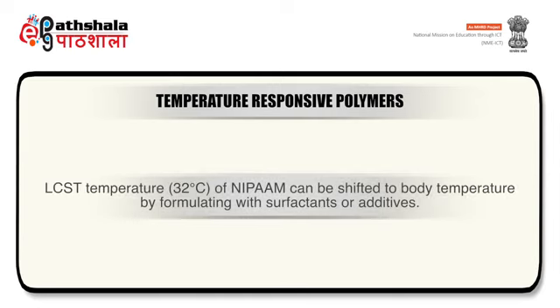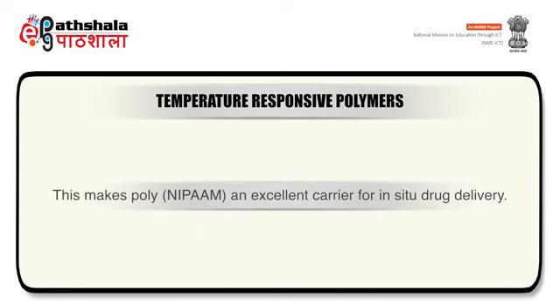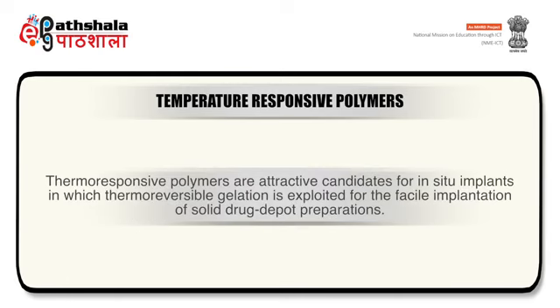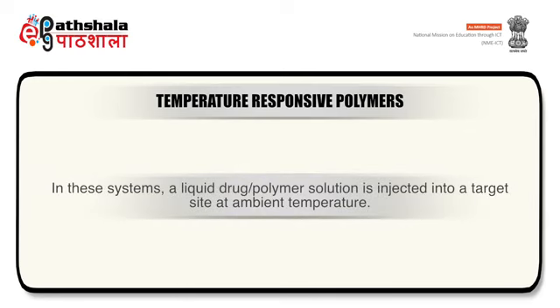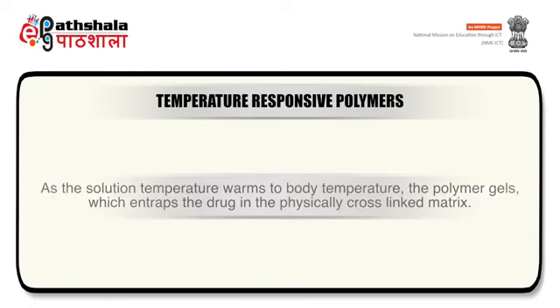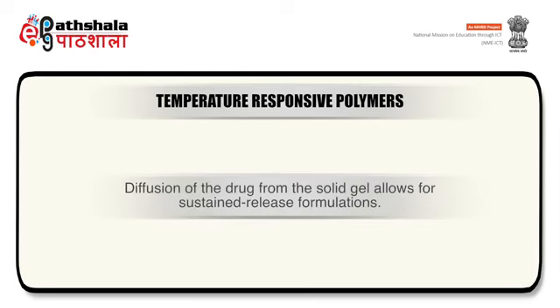LCST temperature of NIPAM, that is 32 degrees Celsius, can be shifted to body temperature by formulating with surfactants or additives. This makes NIPAM an excellent carrier for in situ drug delivery. Thermoresponsive polymers are attractive candidates for in situ implants in which thermoreversible gelation is exploited for the facile implantation of solid drug depot preparations. In these systems, a liquid drug polymer solution is injected into a target site at ambient temperature. As the solution temperature warms to body temperature, the polymer gels, which entraps the drug in the physically cross-linked matrix. Diffusion of the drug from the solid gel allows for sustained release formulations.